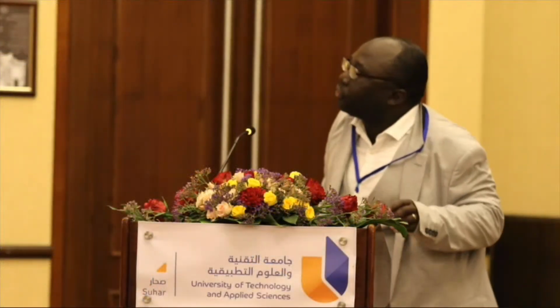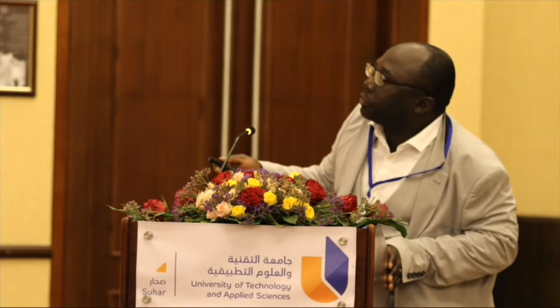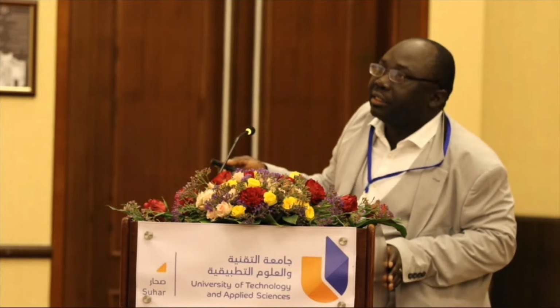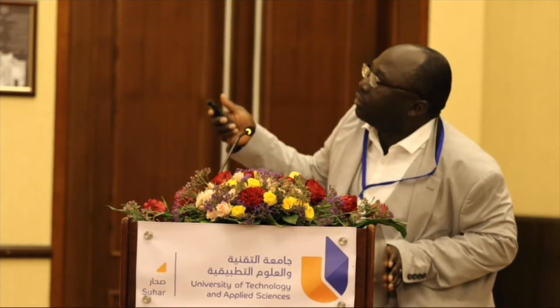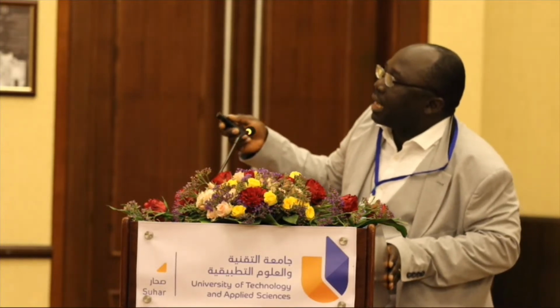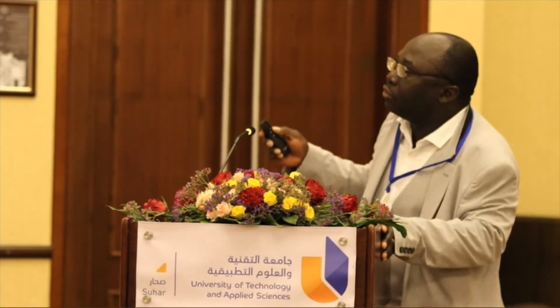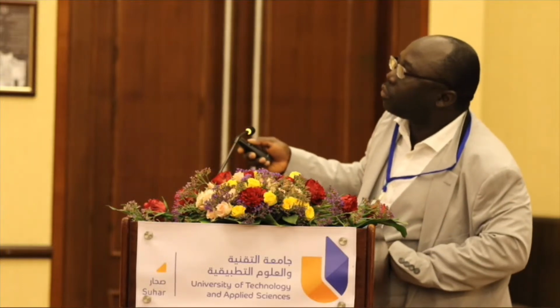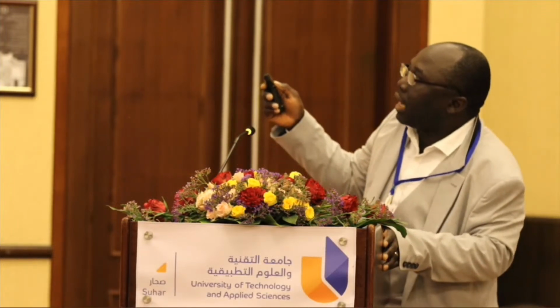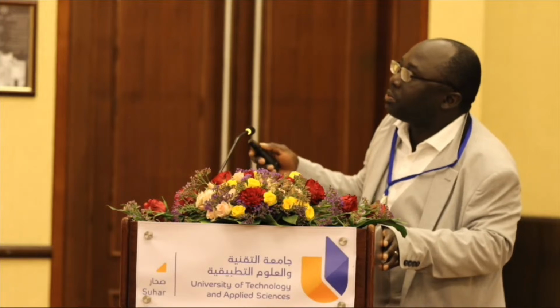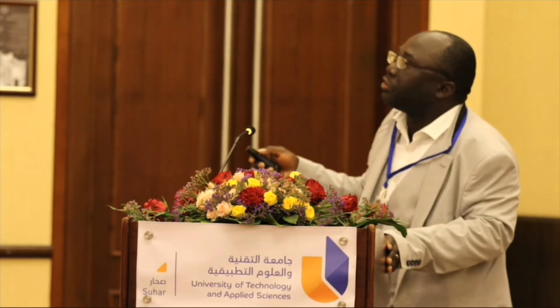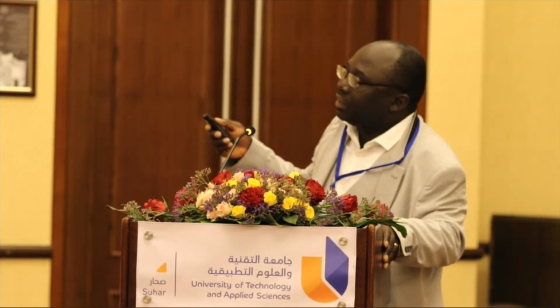Yeah, so in terms of hydrogen transport also, the other point, hydrogen can be transported in different forms, and one of them being compressed hydrogen. And compressed hydrogen is extremely expensive, because the systems can be sized for pressures up to 900 bar. Why you need to transport at extremely high pressure that way is that, as I've mentioned, the volumetric density of hydrogen is very low. So you can see you are talking about around 40 grams per liter at 700 bar, all right? So if you are transporting at a lower pressure, then it's even going to be smaller.